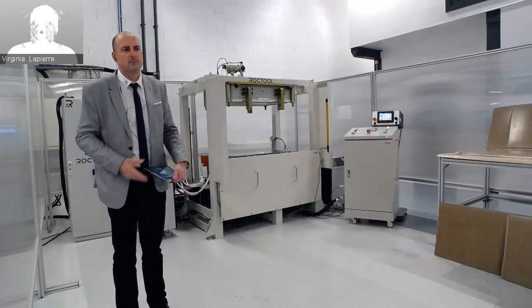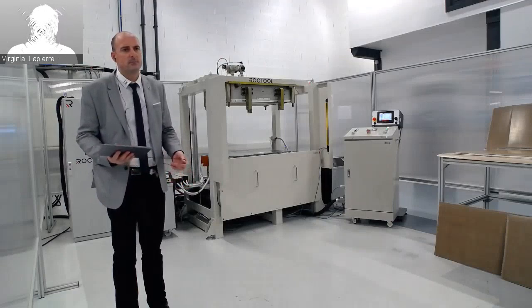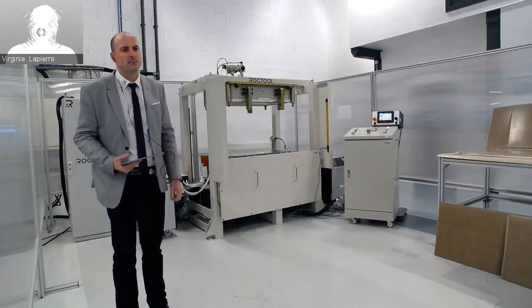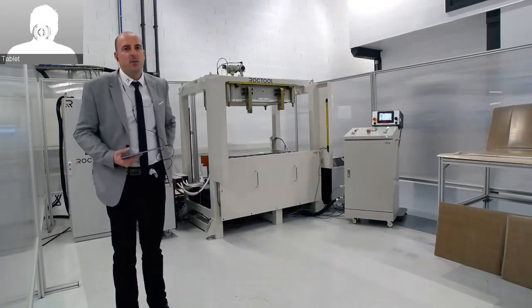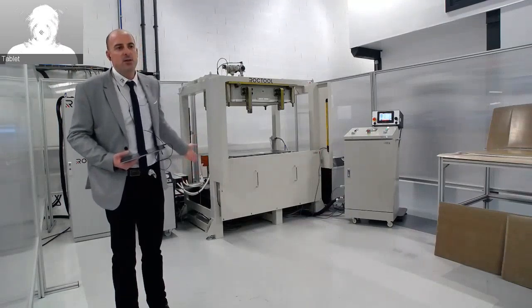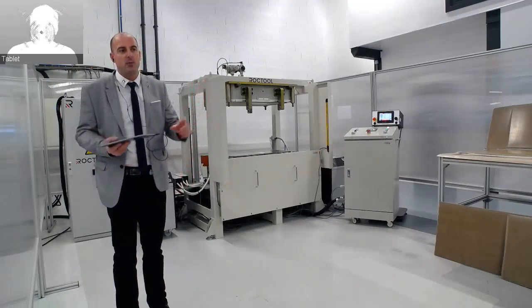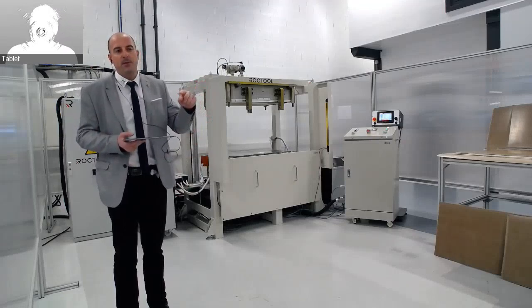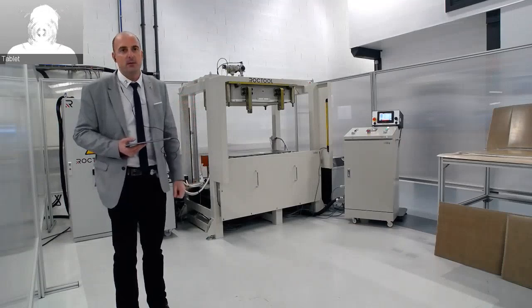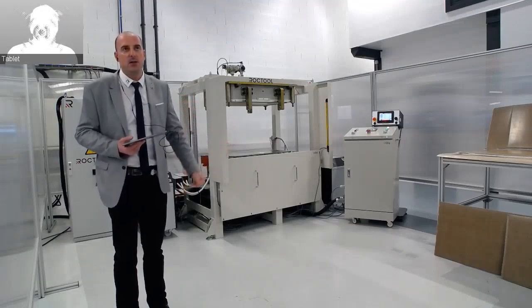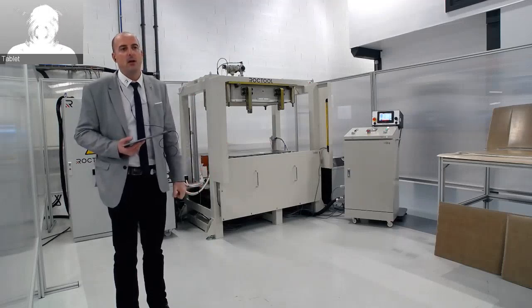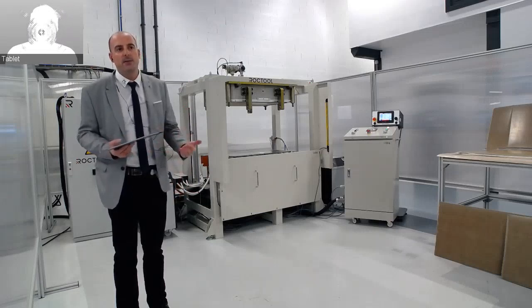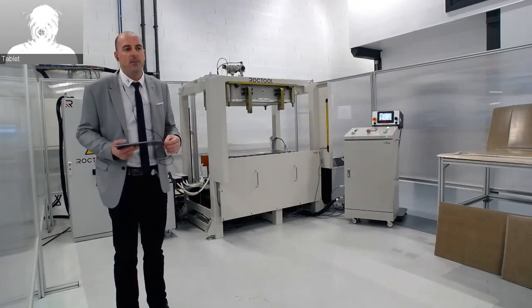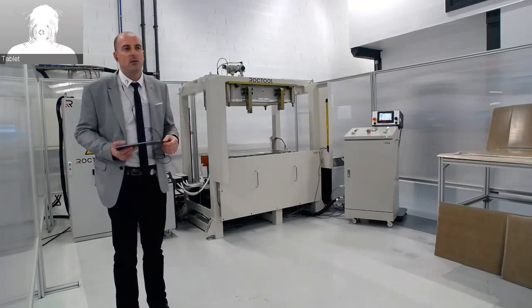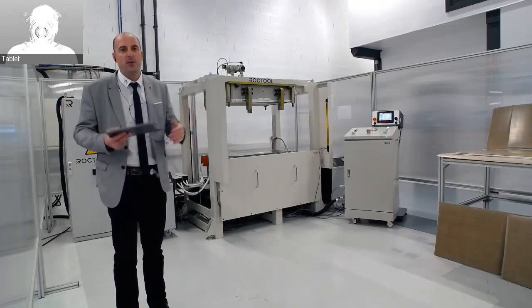What are the limitations on the depth or profile height of the part and how much the membrane can stretch? Any case is possible. I think with this technology, for example, we can produce a 3D geometry part with a depth of more than 200 millimeters for an existing current application, for example, where we have a very important deformability of the product. Of course, we also need in this case a good drapability of material to be able to follow the shape of the 3D geometry part.